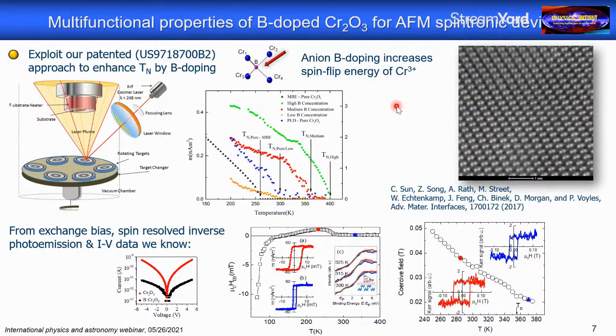And then we did the next obvious thing. We said, okay, now we have an increased Néel temperature. So if we put that into an exchange bias system, we should see exchange bias at higher temperatures. And that was not the case, to our extreme disappointment. I show you just a few data that show this. Here we put a perpendicular ferromagnet again on top of boron-doped chromia. And you see that the loop width of this ferromagnet does get bigger once the antiferromagnetic ordering sets in. That is an indication that your ferromagnet is sitting on an antiferromagnet that has ordered, and that the ferromagnet and the antiferromagnet are interacting with each other. But this interaction was not strong enough to actually pin the ferromagnet and create a sizable exchange bias.